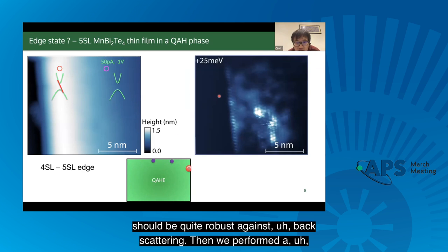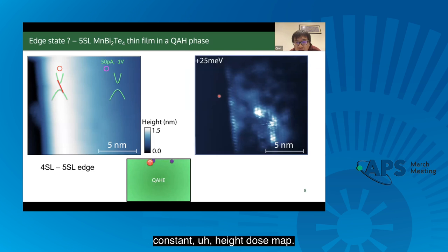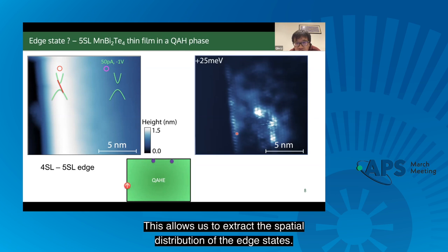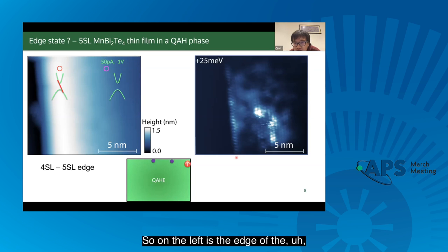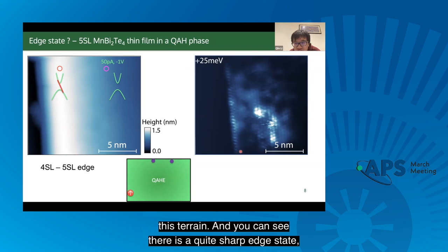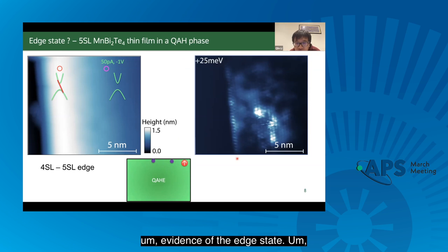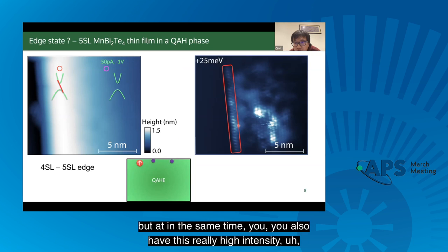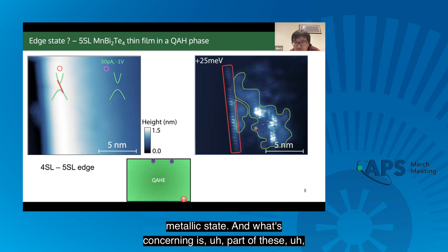Then we performed a constant height DOS map. This allows us to extract the spatial distribution of the edge state. On the left is the edge of this terrace, and you can see quite a sharp edge state. But at the same time, you also have this really high intensity metallic state. And what's concerning is that part of these metallic states is also coupled to the edge state,